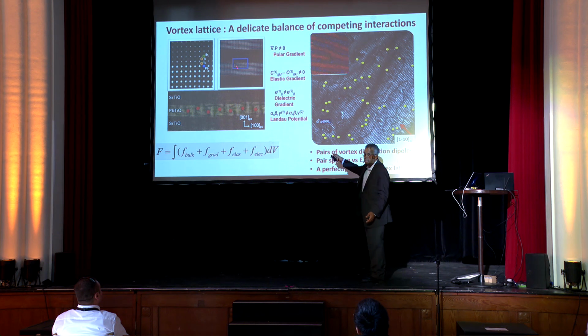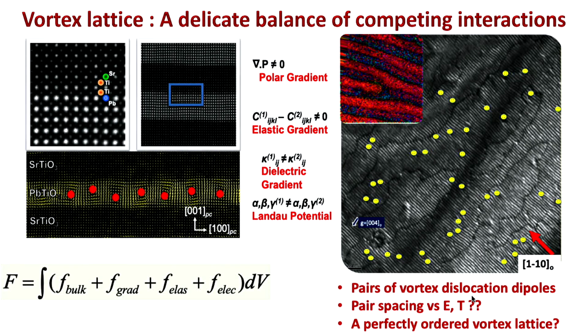In this case, 10 unit cells of lead titanate. You can see the brighter contrast. Lead is a bigger atom, so you see that. And 10 units of strontium titanate. Now, if you look at it with a little bit more care, which means you start to do detailed analysis of the atomic position, what you see is that the lead ions, or the titanium ions for that matter, are not fixed. They're actually spiraling. Not that they're moving around, but they're spiraling in space. Okay? And that's shown here in this part.